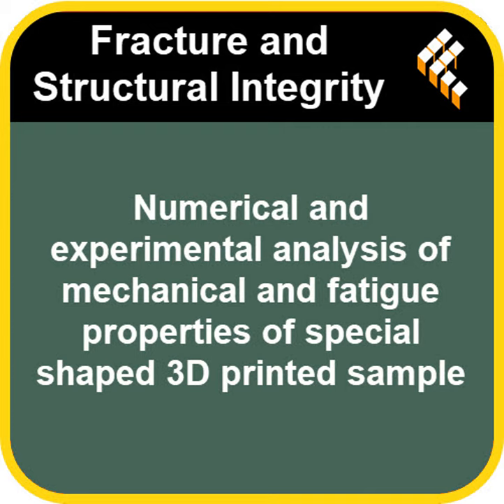They use this established curve for polycarbonate to predict the lifetime of their specific printed part based on the peak stresses the simulation showed occurring during the cycles. And based on their analysis of the simulation, where did they find the highest vulnerability? Where were the stresses concentrating under that cyclic load? Well, interestingly, the stress concentrators, the points of highest critical stress under cyclic loading, were found right at that same edge level, where the inner and outer structures of the special geometry met. The same place it broke in the single pull test.